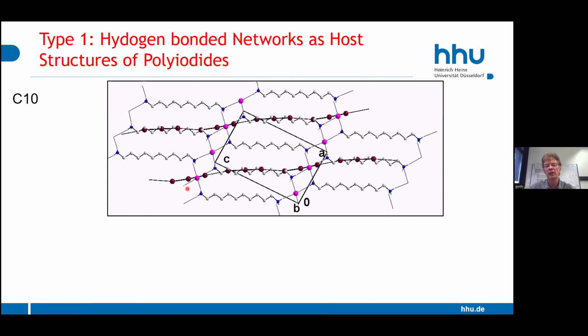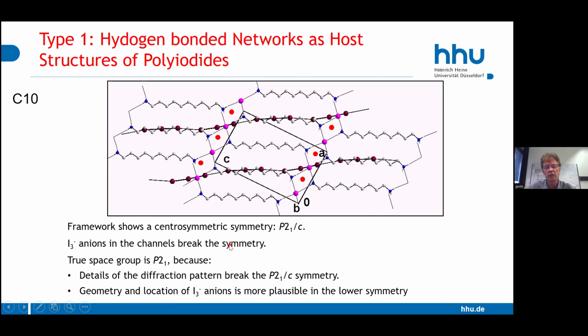I want to show you why it makes a lot of problems, and I had a lot of discussions with the reviewers in those times, because the framework that produces this host framework has a centrosymmetric situation. That means that the framework has inversion centers here at these dots, where these red dots are. But you directly see that the I3- ions are not fitting with the inversion symmetry. So we have a reduction of the true symmetry, and the true symmetry is P21.